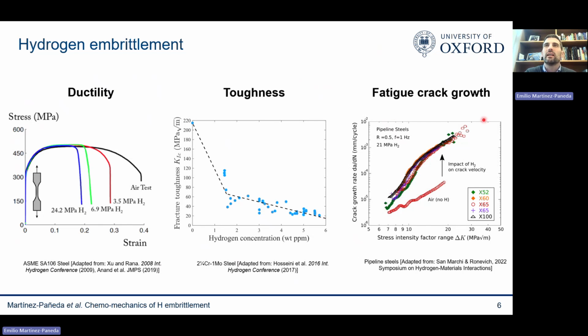The effect is also quite significant on fatigue crack growth. You see this here. These are for pipeline steels exposed to hydrogen gas. This is the log-log plot. This is the response in air, and this is over the Paris law regime, the response in hydrogen. You can see that there's at least one order of magnitude elevation in fatigue crack growth rates.